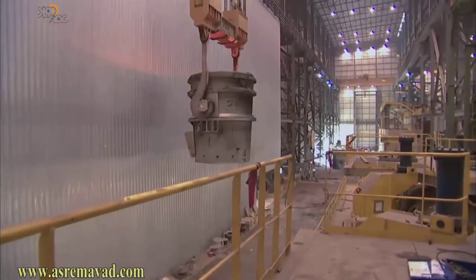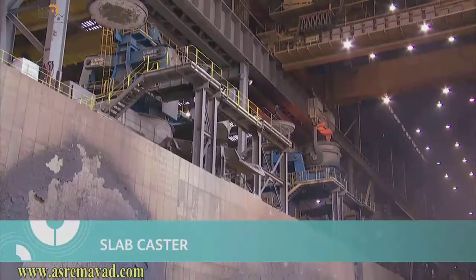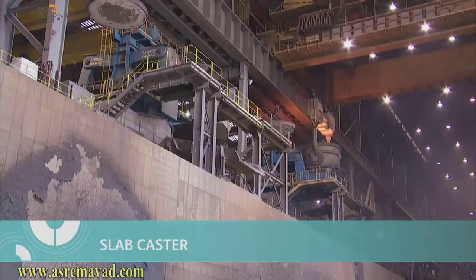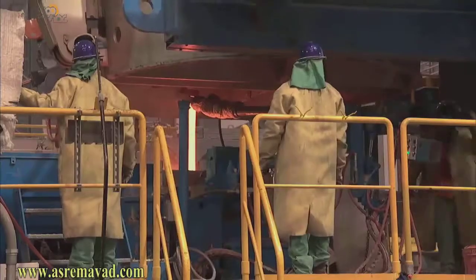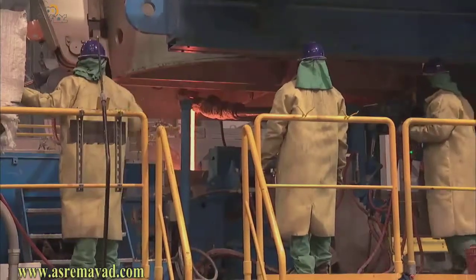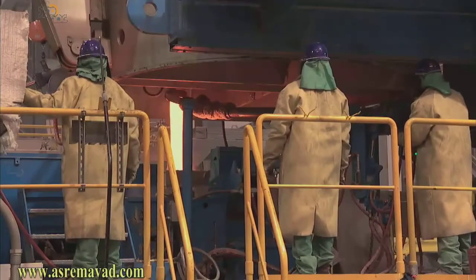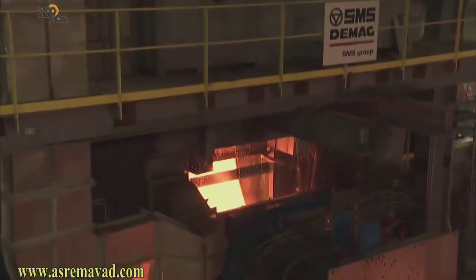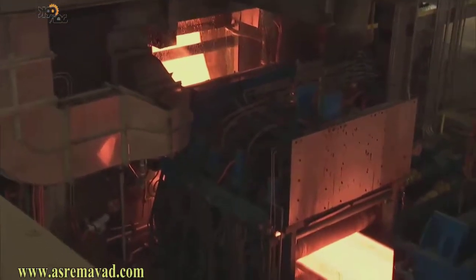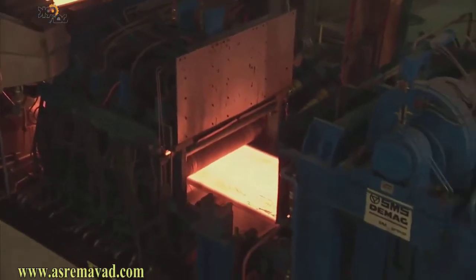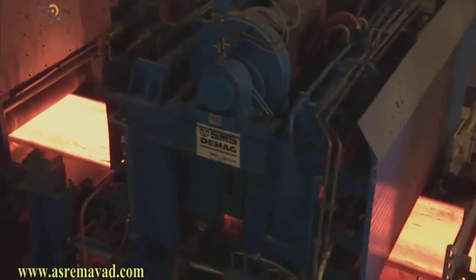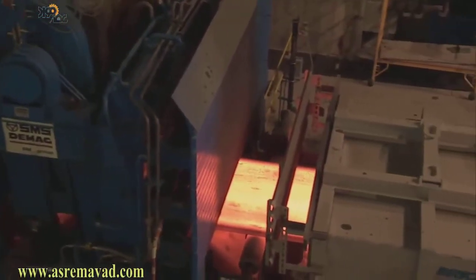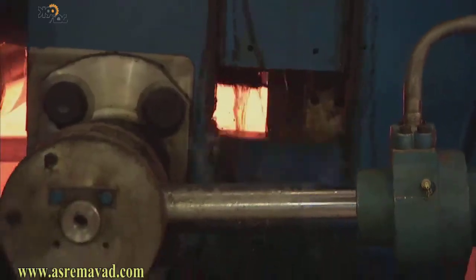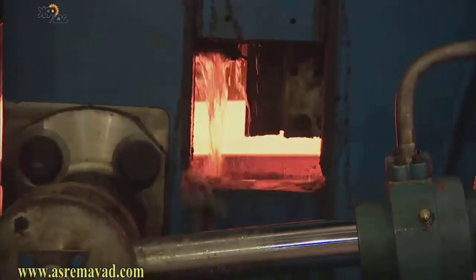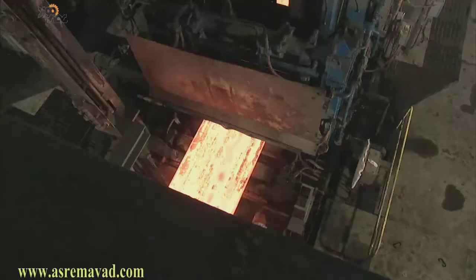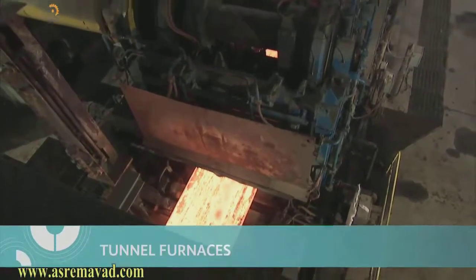From the LMF, the ladle of molten metal is moved to one of the facility's 2 thin slab casters. A bottom spout allows the ladle to pour the molten metal into a tundish, or reservoir, and ultimately into a casting mold. Descending nearly 7 stories, the molten metal traverses down the mold's water-cooled walls, which harden the metal into a semi-solid slab of steel. At the bottom of the caster mold, the slab is sheared to a length corresponding to the customer's order and moved slowly into the attached tunnel furnace.